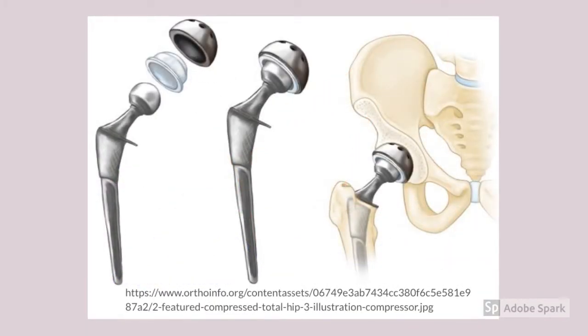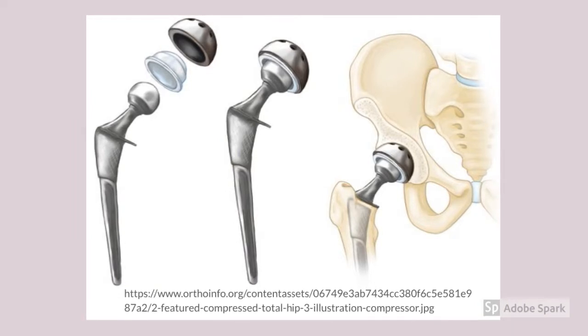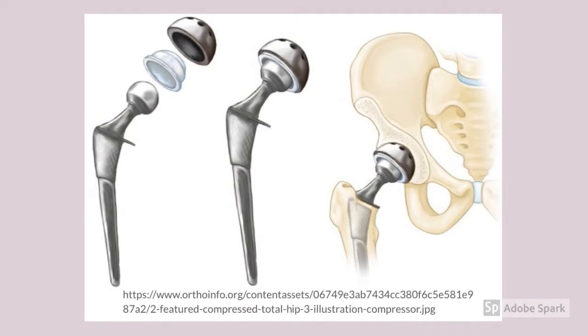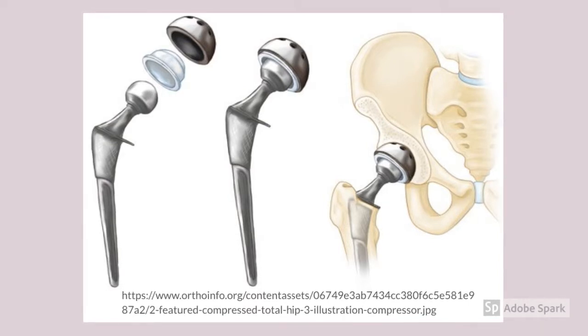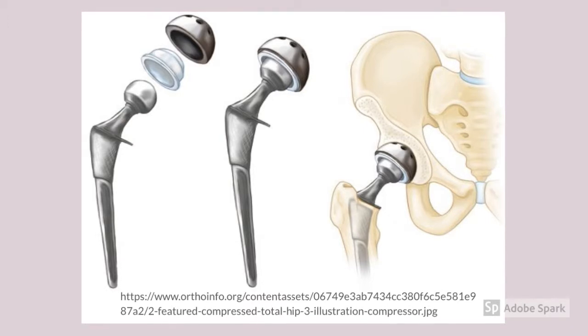One of the main concerns involving hip implants is the degradation of the polyethylene cup that serves as a socket for the joint. If debris from wear of the polyethylene enters the joint, osteolysis can occur and the weakened bone will not be able to provide enough support for the implant. Thus, the implant will become loose and unstable. Cross-linked polyethylene was introduced to reduce degradation and therefore the failure of the implant.